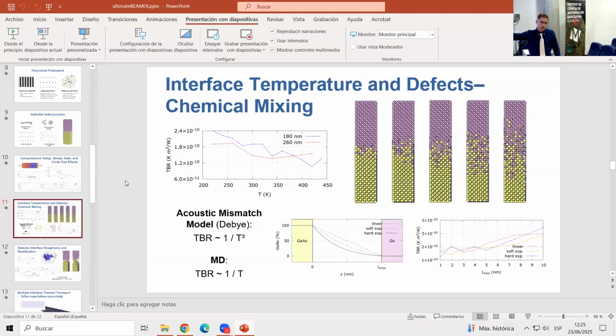They should kick in. Indeed, without phonon interactions and impurity scattering, you would observe an infinite thermal conductivity for every material. So in order to observe a finite thermal conductivity, you need interactions. Here you are taking interactions at every order into account. So maybe something about third and fourth order phonon processes becoming more enhanced at higher temperature provides a better compatibility between the two spectra. So it's easier for the phonons to pass from one side to the other, and that's why we don't observe such a sharp drop. But this is a very difficult answer.